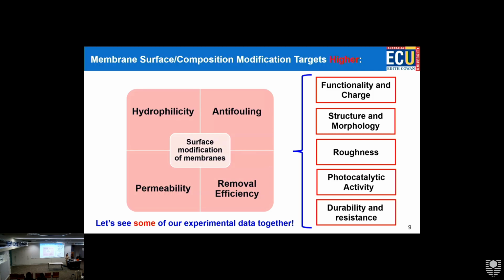Yeah, that's right. Attract water, it loves water. So when you have more hydrophilic membranes, majority of contaminants are hydrophobic, basically. Even majority of microplastics are hydrophobic, so they don't like water. So if we make membranes more hydrophilic, when the membrane is in touch with water, a very, very thin hydration layer is formed on the surface, and this hydration layer repels those hydrophobic materials, basically.